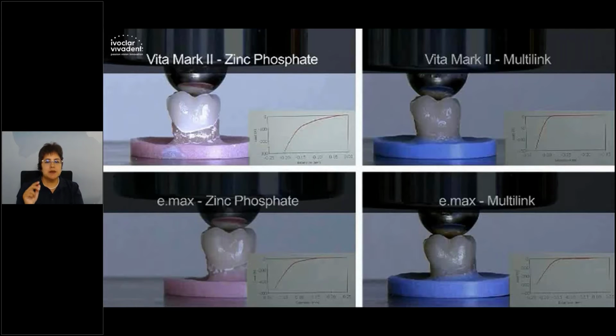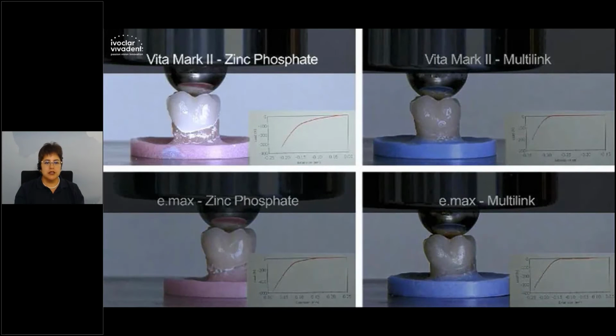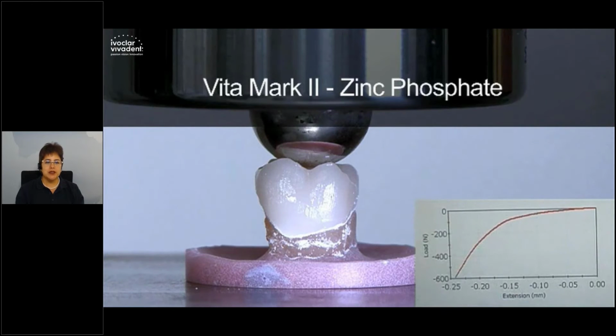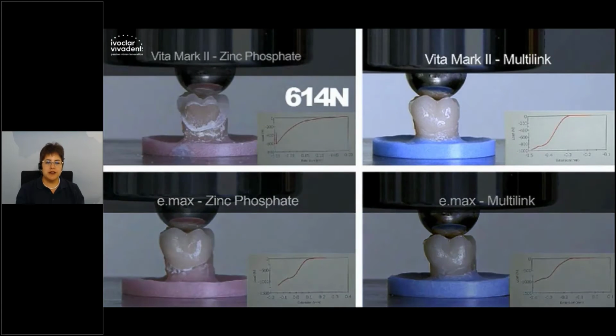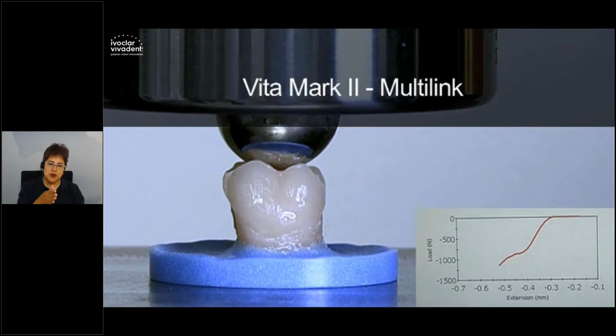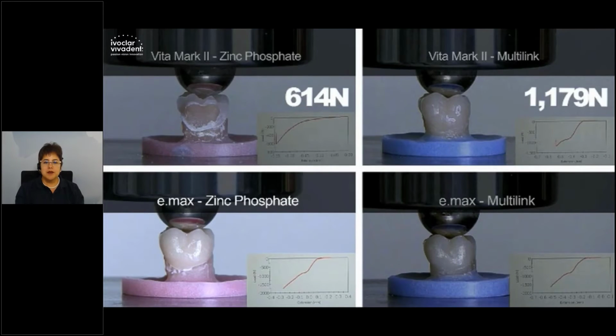Here you see two types of monolithic restorations. On the upper side, we have Vitablocs Mark II, and on the lower side, we have IPS e.max CAD restorations, our lithium disilicate glass ceramics. On the left-hand side, we cemented conventionally. On the right-hand side, we cemented adhesively. There is a test where you measure the fracture toughness of a restoration material, and this test is to increase the loading until the crown will crack. So here you can see that the feldspathic crown luted conventionally will have a load of about 600 Newton. If you're using the same crown but adhesively, you need double the force.